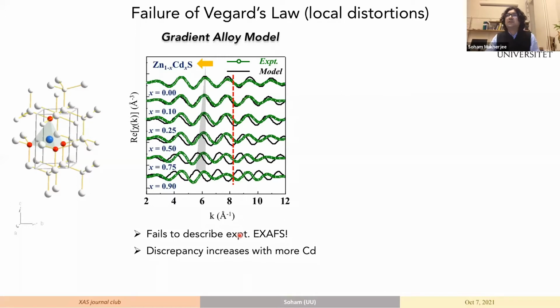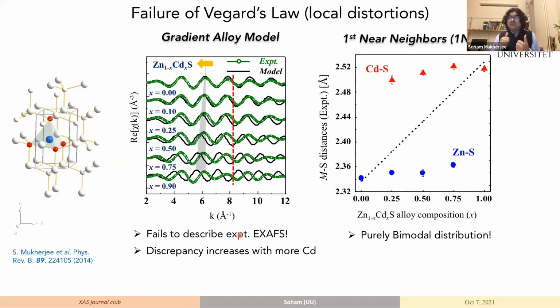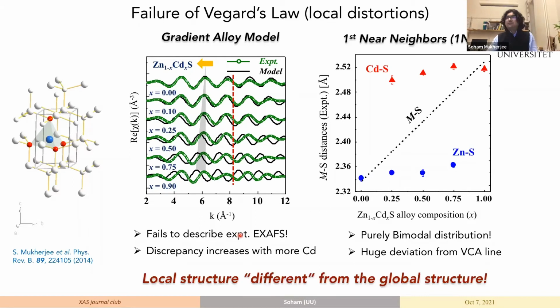So we probed the zinc and the cadmium edges separately at the APS, and we immediately saw that there's a purely bimodal bond distribution instead of an average bond length. So now this clearly says that the local structure is different from the global structure. And there is something funny going on, because you have two different structural solutions to one particular solid.